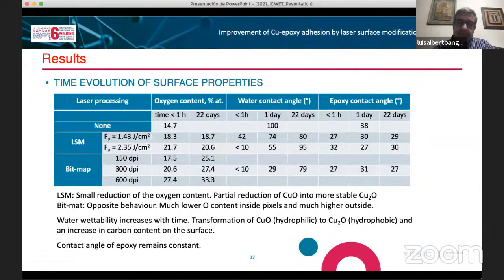We have been checking different properties to know how they can be affected by time. First, we have been checking the oxygen content. In principle, we see that the oxygen content reduces with time in the case of the line scanning mode. This could be due to the partial reduction of the copper oxide into the more stable copper 2 oxide. In the case of the bitmap, we have the opposite behavior. Usually the oxygen content increases, and we have tried to explain this by a transformation of the copper oxide hydrophilic phase also into copper 2 oxide. We have also observed an increase in carbon content on the surface.